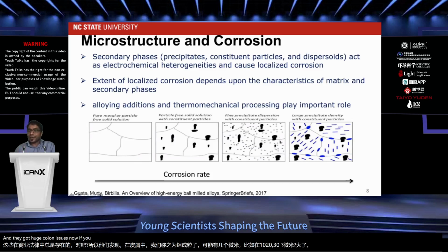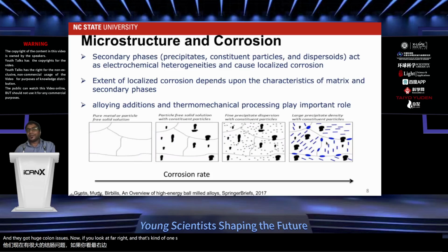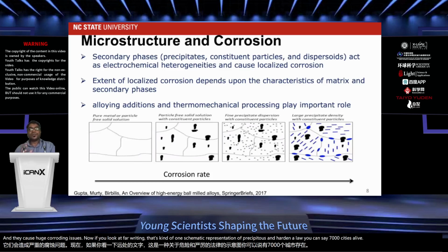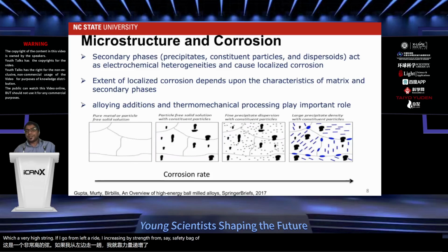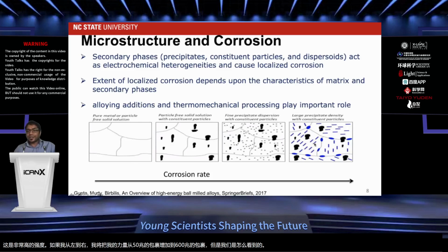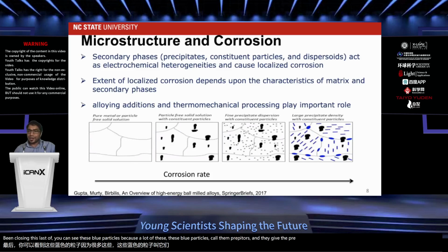Now, if you look at the far right, that's a schematic representation of a precipitation hardened alloy. You can say 7000 series alloys, which have very high strength. If I go from left to right, I'm increasing my strength from say 50 megapascal to 600 megapascal. But how are we achieving that? We're increasing the number of these blue particles, which we call precipitates, and they give the precipitation hardening.